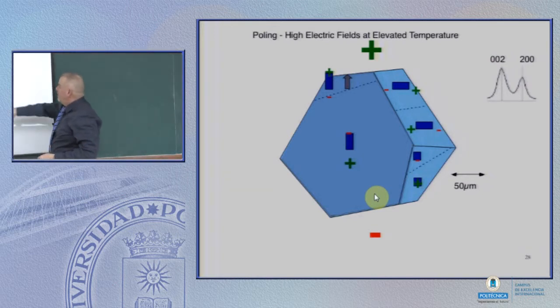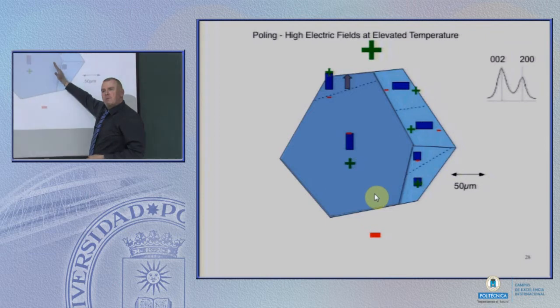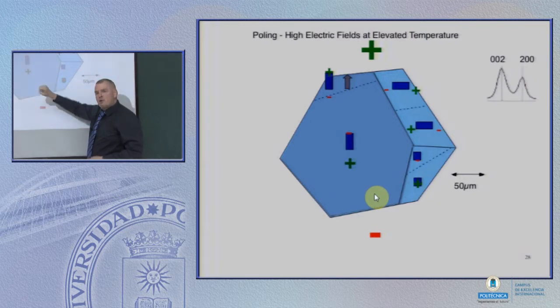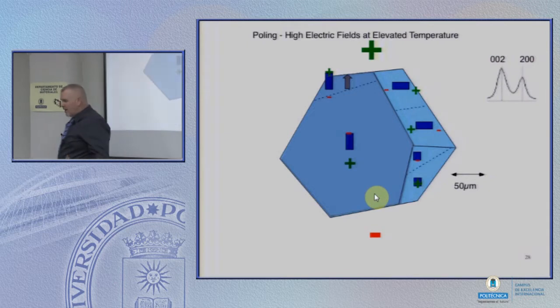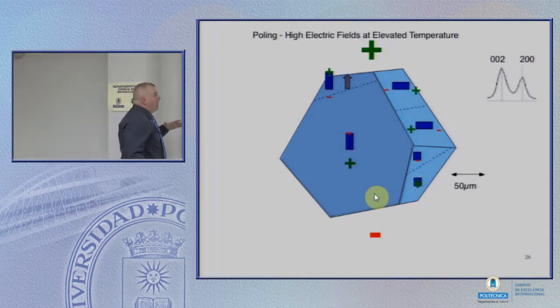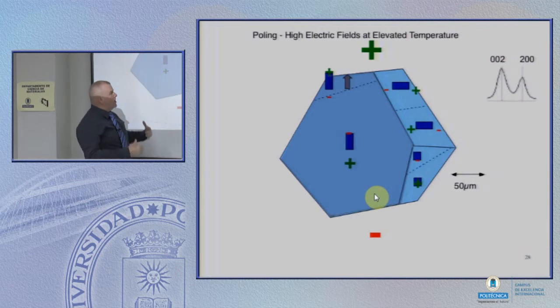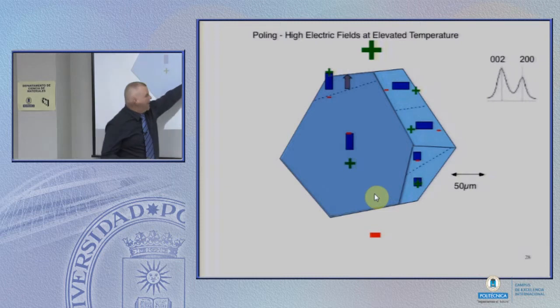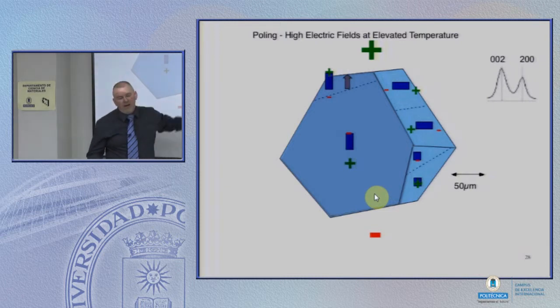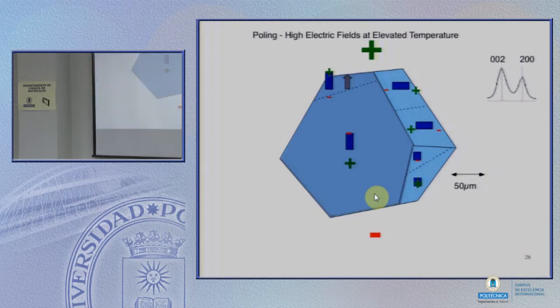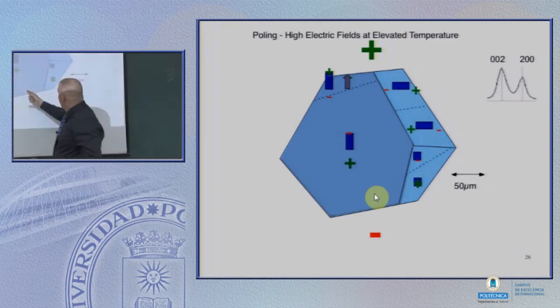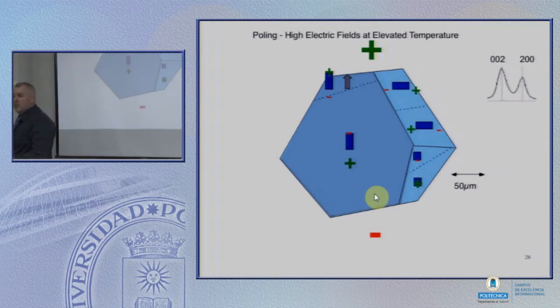And that's actually the measurement that we make most often, on how much of this domain boundary motion has been made. And not just in crystals that are this orientation, we also do it for crystals that are all the other orientations. So we then try and understand what's taking place in the material. Pretty simple calculations you can do to find this relationship. Essentially, if we were to take this all the way to the final edge here, we can have essentially three times as much of what we had initially for this individual crystal.